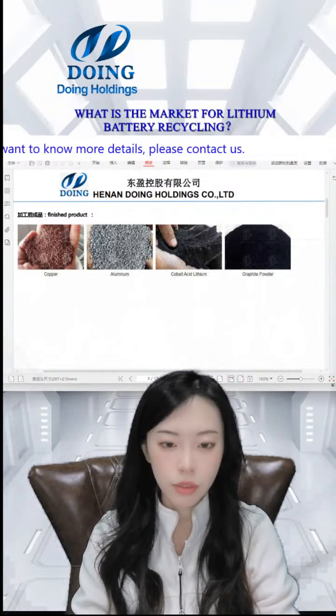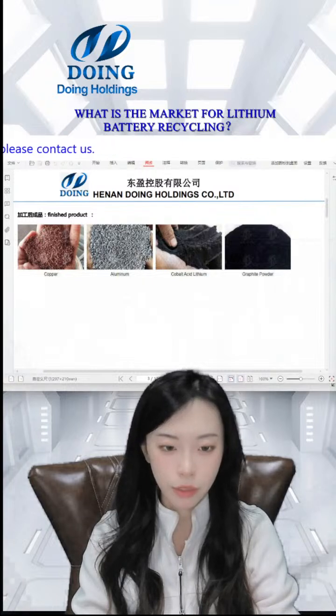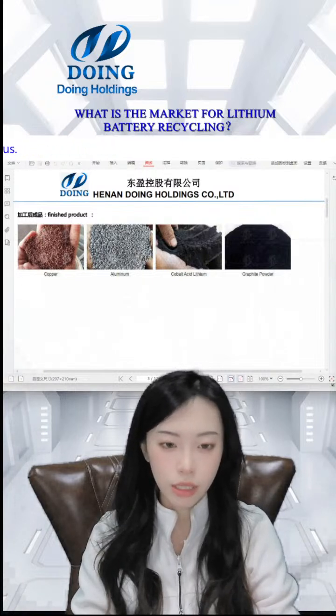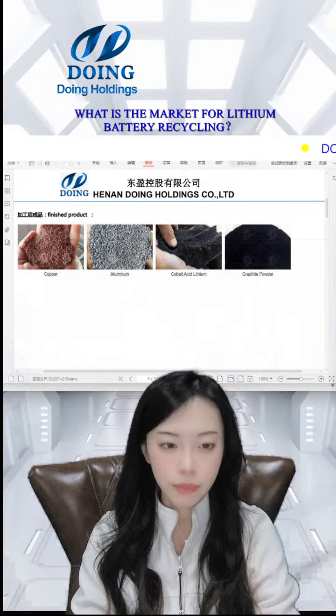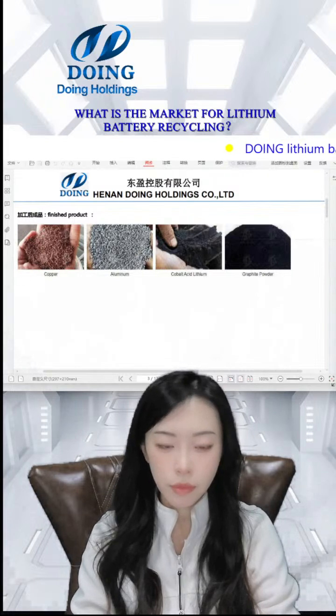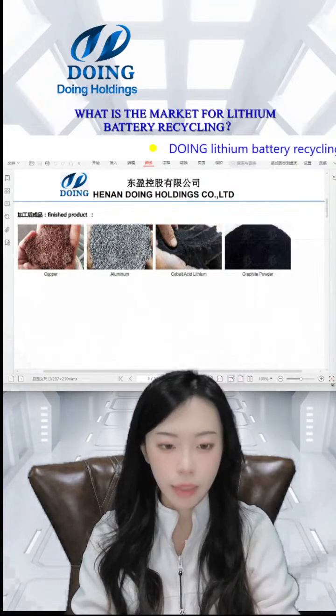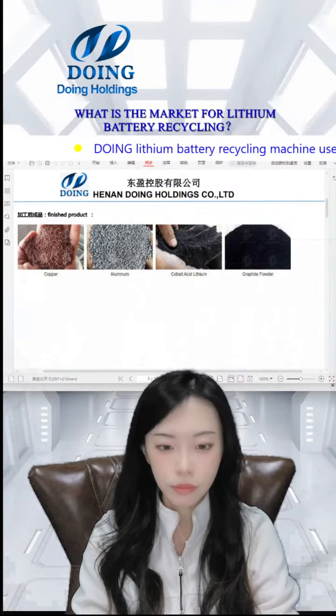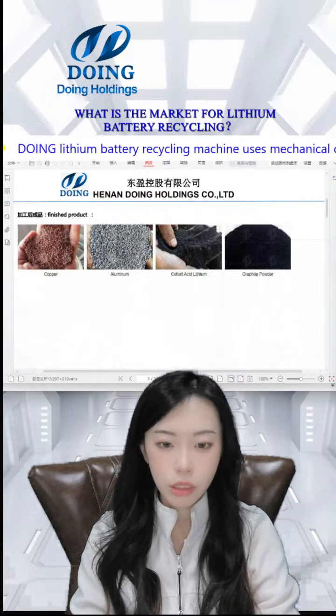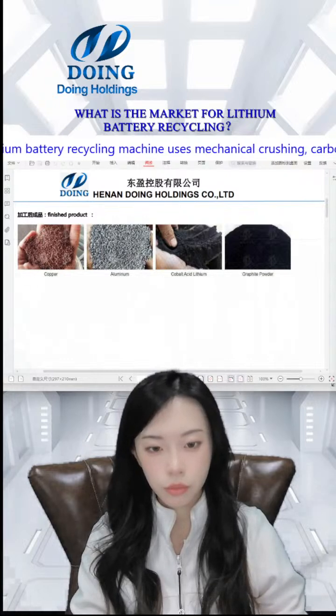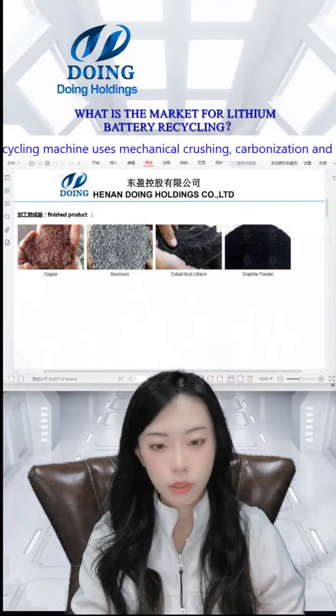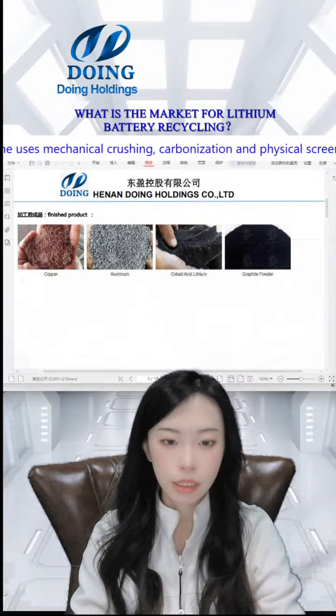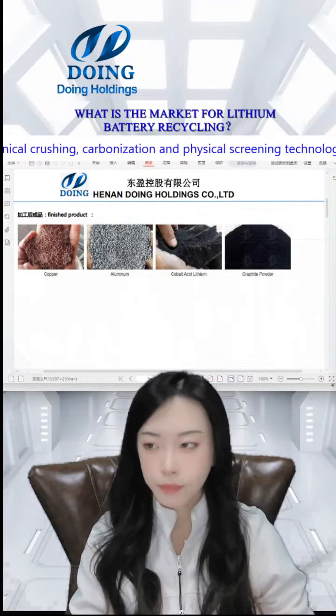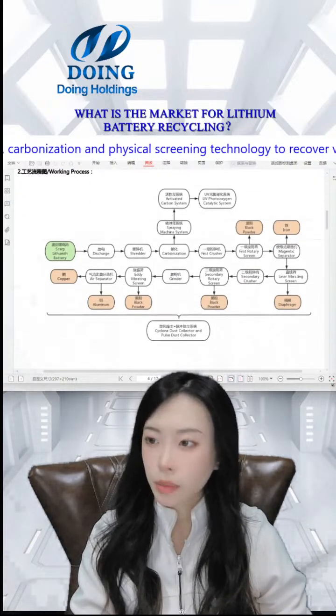The top layer of the screen is diaphragm, the middle layer is copper, aluminium, black powder, and the bottom layer is to collect all the black powder. And here the diaphragm recovery is 98%. Then the black powder will be collected at more than 98% in the ID vibrating screen. Here is the working process.